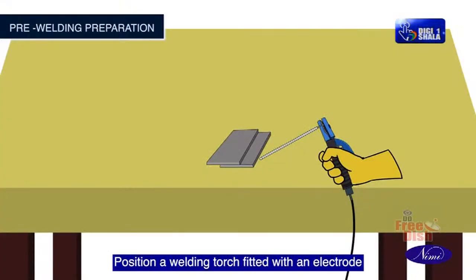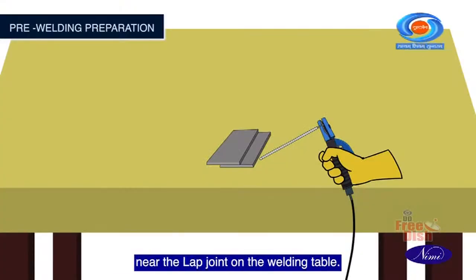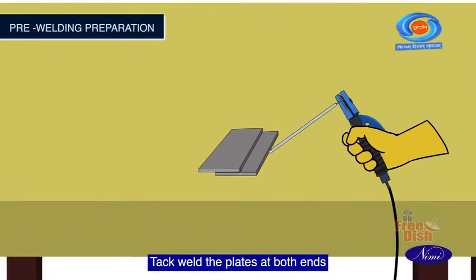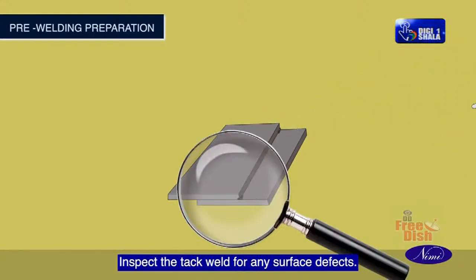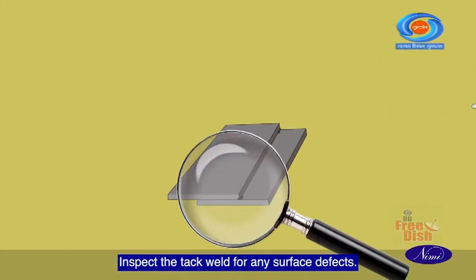Position a welding torch fitted with an electrode near the lap joint on the welding table. Tack weld the plates at both ends with a 3 mm tack size. Inspect the tack weld for any surface defects.